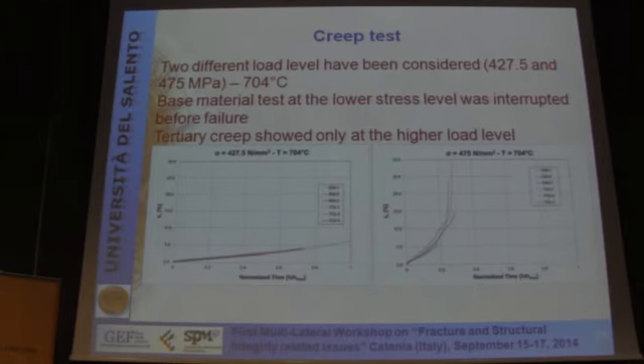Finally, we carried out also several creep tests. We considered two load levels and a temperature of 704 degrees. Base material tests were interrupted before arriving at failure, and we observed a tertiary creep only for the highest load level.